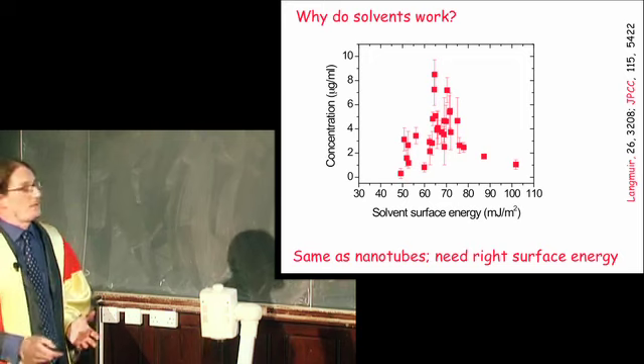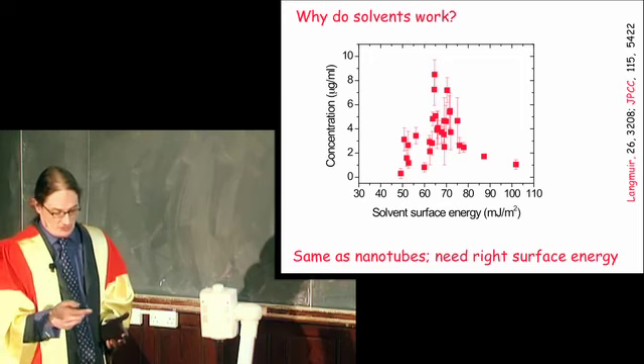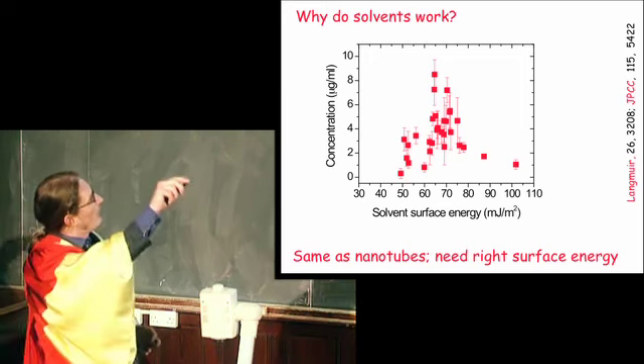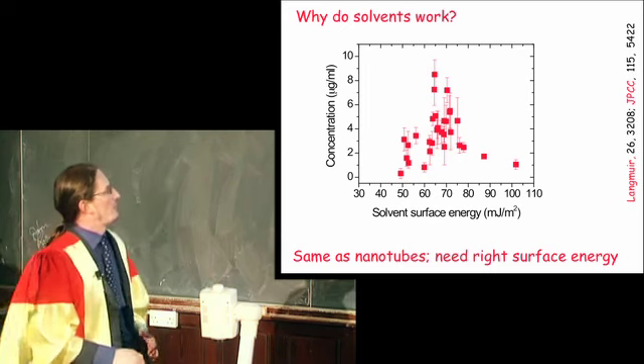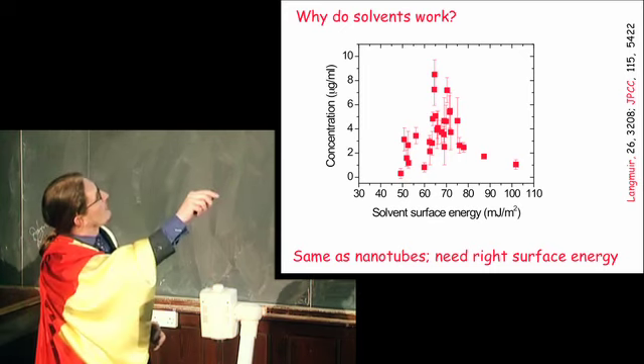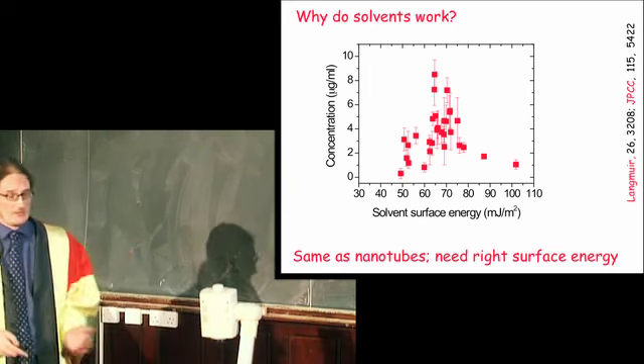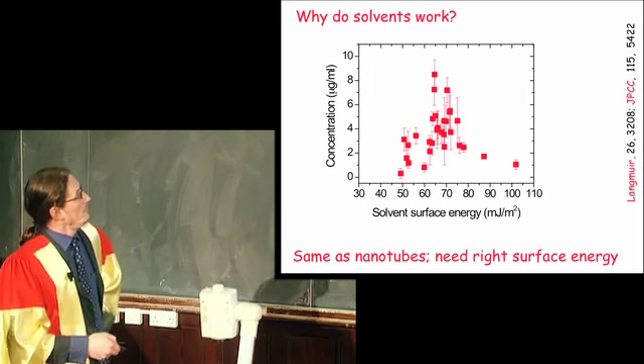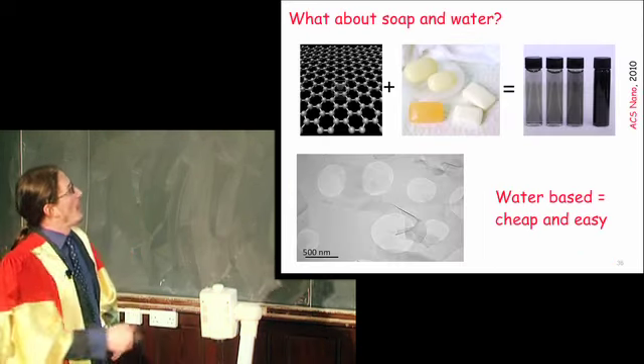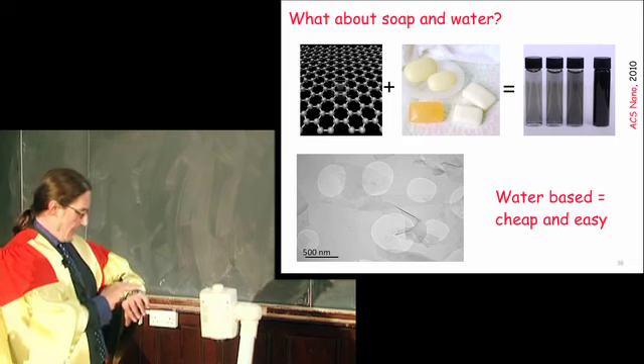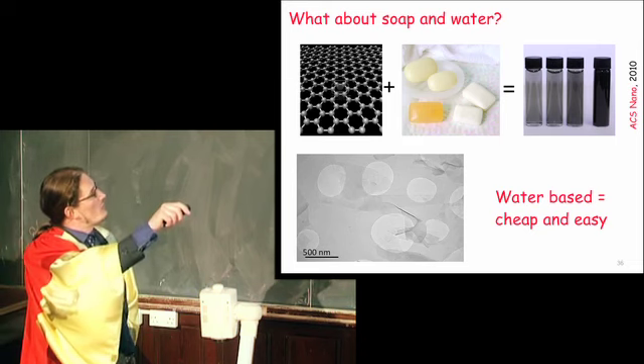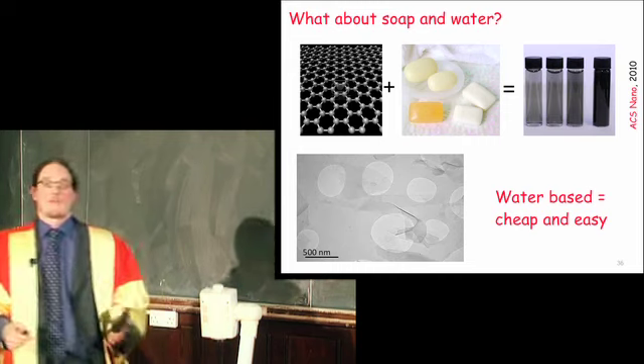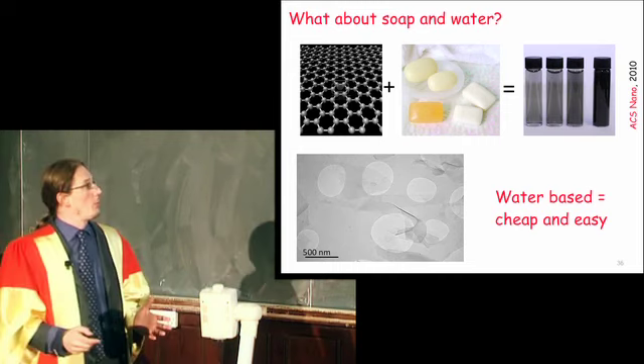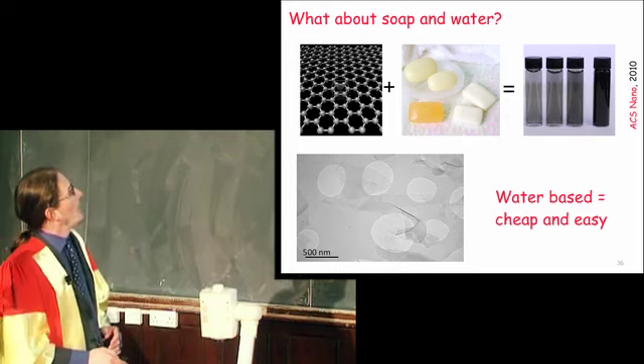Now, why do solvents work for graphene? Well, it's just the same as carbon nanotubes. If you get the surface energy of the solvent right, such that the surface energy matches the surface energy of graphene, which is known to be around here, you get lots of stuff dispersed and exfoliated. What about soap and water? Well, you can take graphene, mix it with soap, you get a black liquid, you look in with the microscope, and you get graphene sheets. So it works with soap and water as well as with solvents.